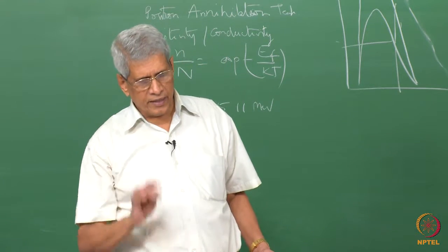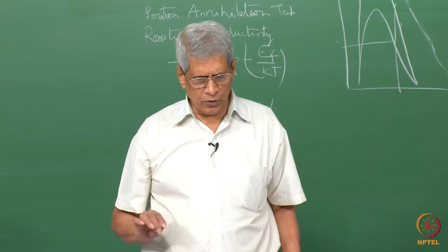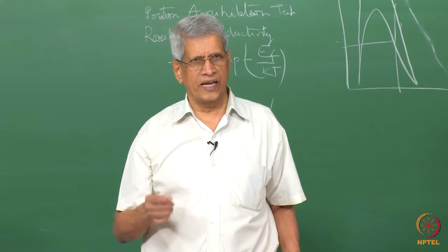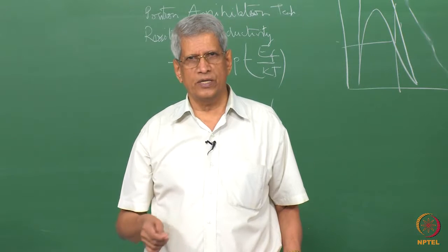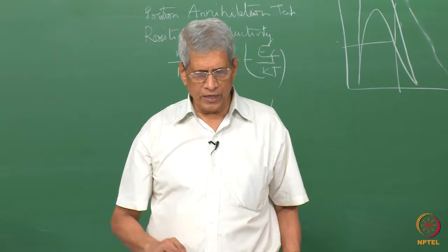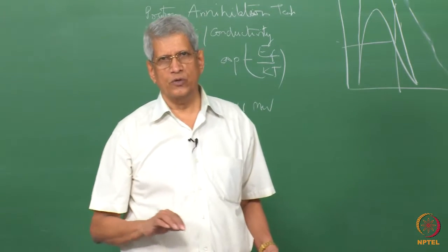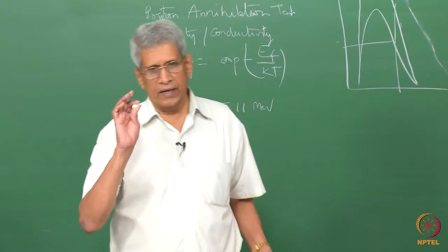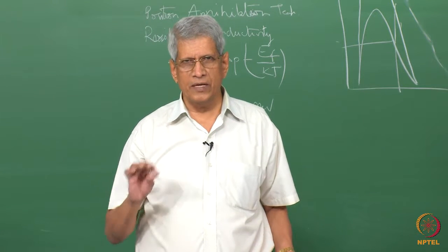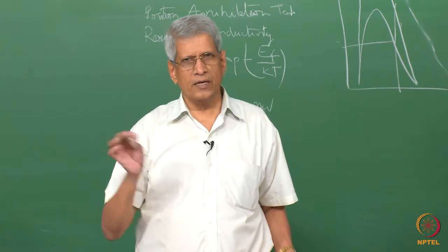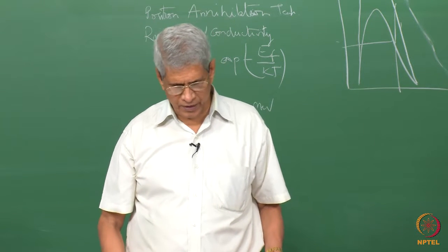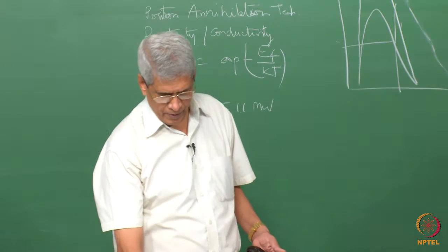And generally the contribution to resistivity from the lattice vibration is going to be very high. So, if you have to reduce it, you do the experiment at very low temperatures. So, by lowering the temperature, what are we trying to do? The contribution due to lattice vibration is reduced. Now, the major contribution is coming only from the defects which are present in the material.